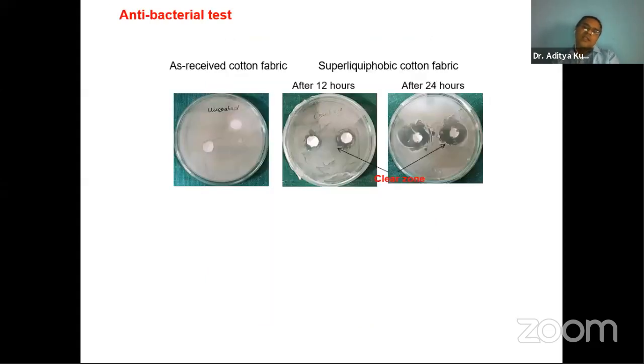All right. Another is antibacterial. Here we also demonstrate the antibacterial nature of the super hydrophobic surfaces. This cotton fabric, after we put it into the bacteria and incubation, what we observed, the bacteria is all over the cloth surface, but in the case of the super hydrophobic surface, it makes a clear inhibition zone. That is significant. So after coating, the bacteria do not come to the surface, or the surface easily kills them. Right.